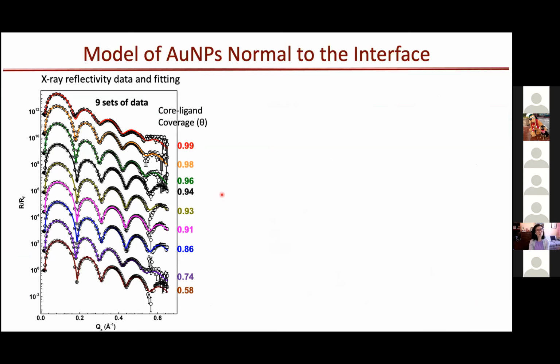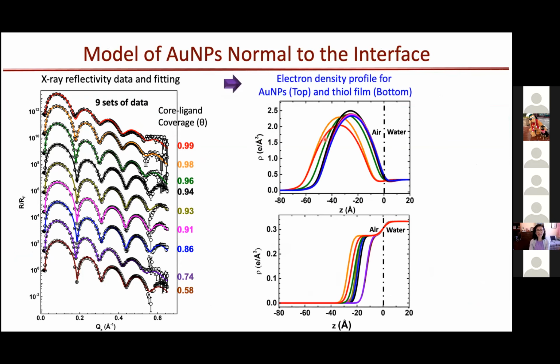Here we show the fitting results for the 9 sets of data, and the electron density profile for this fitting: gold nanoparticles on top, and thiol film at the bottom. This is the direction indicating theta increasing for the data.